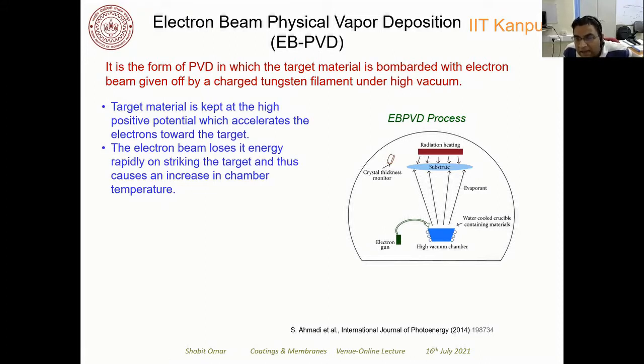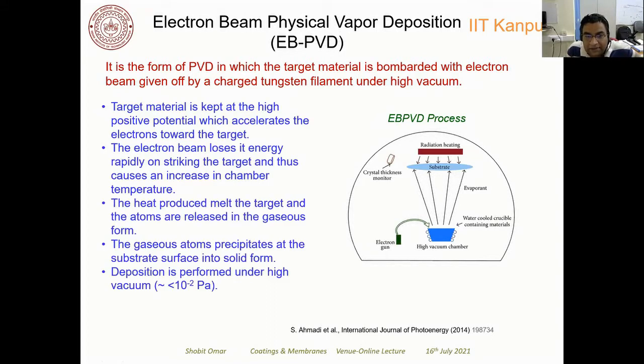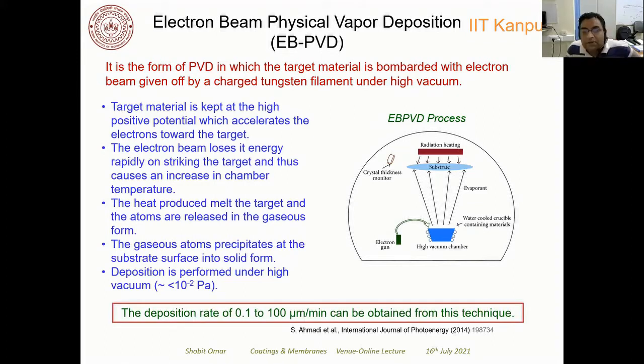and then the temperature increases, and as a result the heat produced melts the target, and the atoms are released in the gaseous form to form a thin film on the substrate. So these gaseous atoms precipitate at the substrate surface into solid form. The deposition rate is around 0.1 to 100 micron per minute, and that is what we can obtain from this